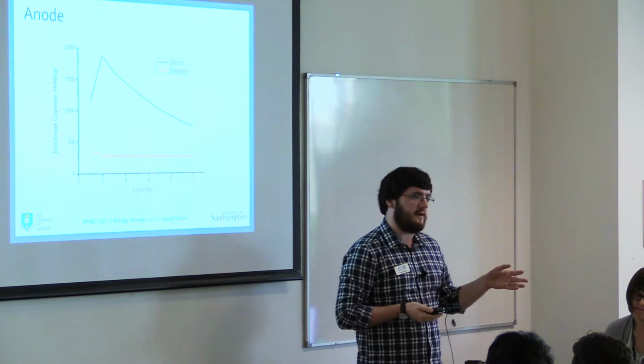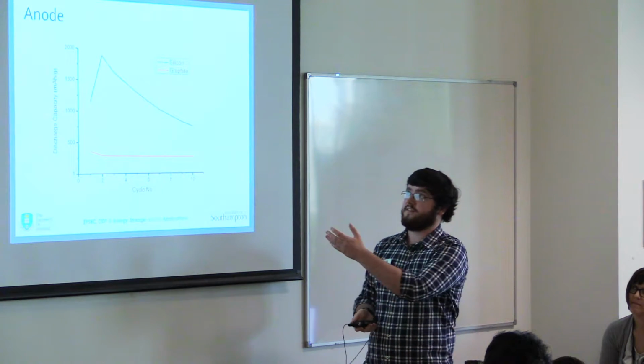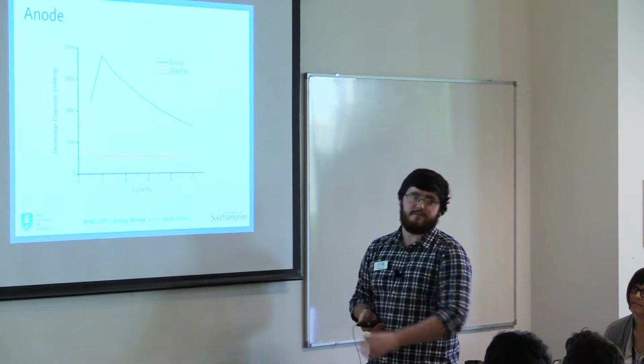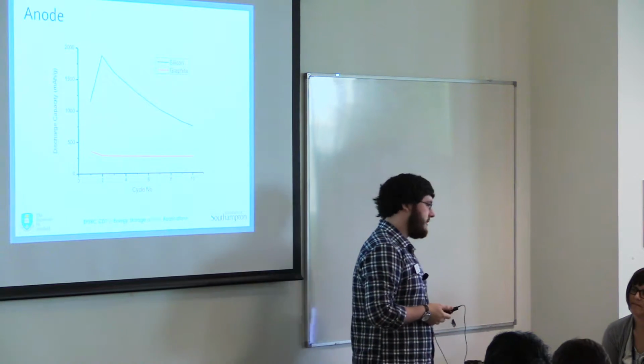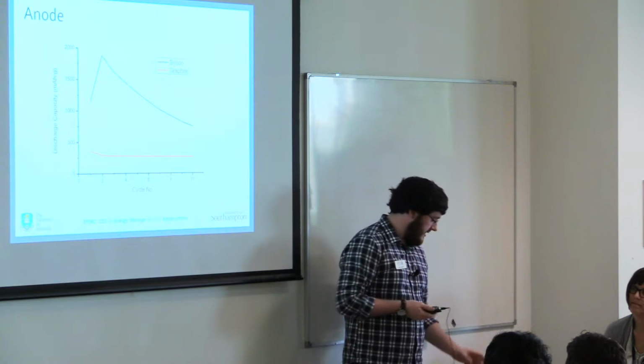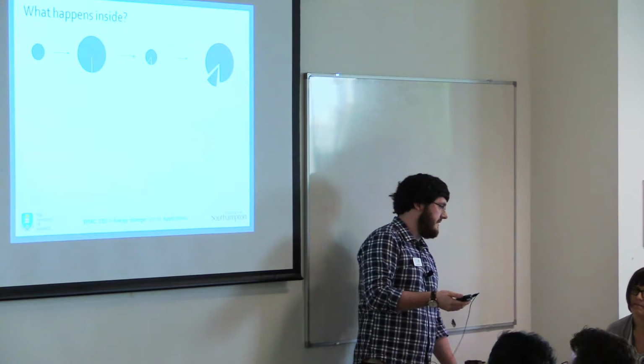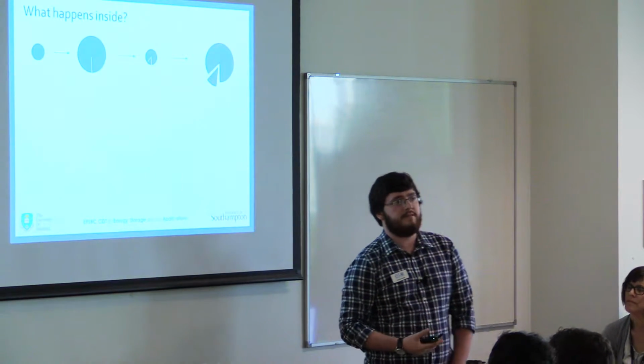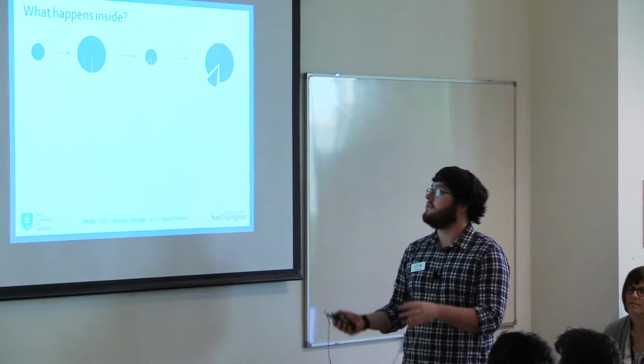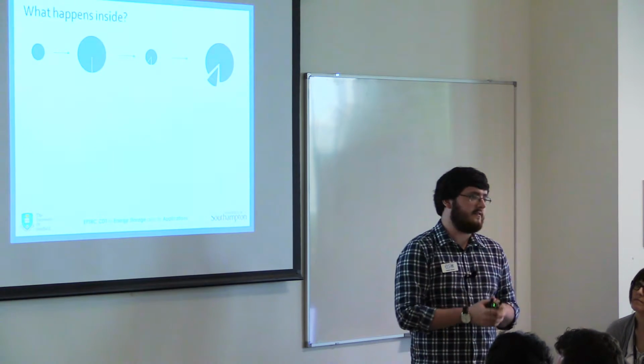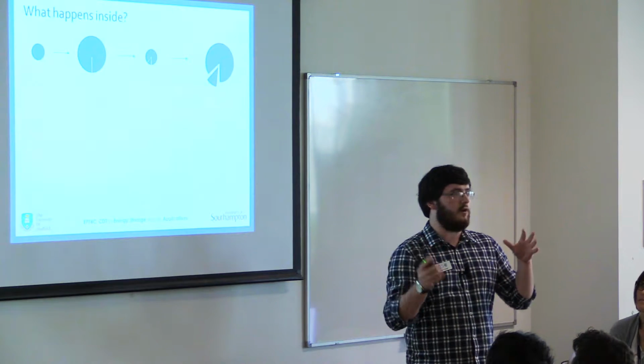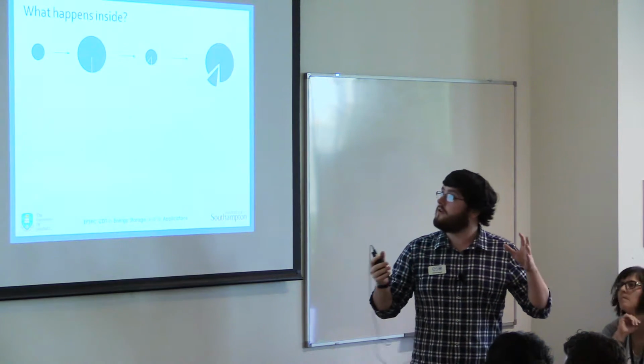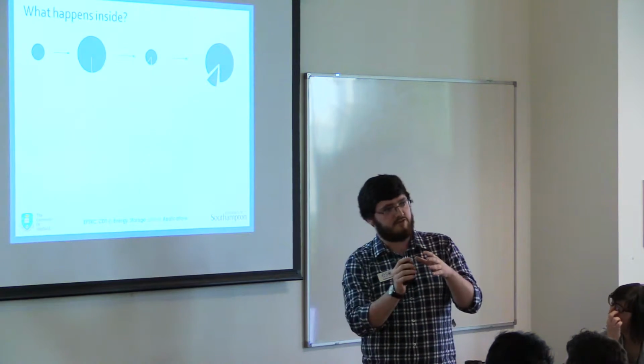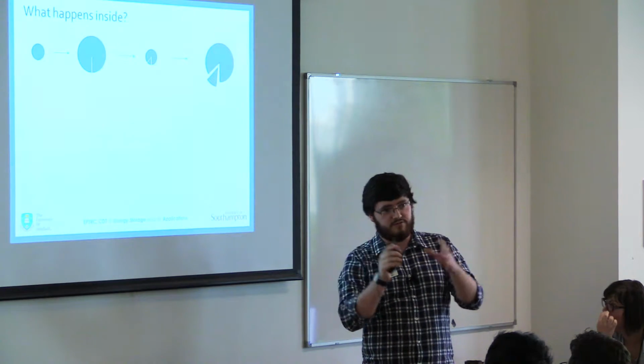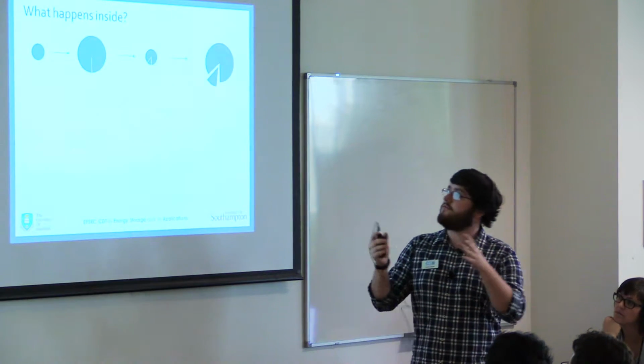I wish to increase the capacity of lithium-ion cells by using silicon anodes, but obviously we've got severe cyclability issues. So how do we go about this? First we have to understand what's going on inside the cell. When you're charging your cell, the lithium ions enter into the silicon structure. The silicon structure expands, increasing in volume by about 400%. You then discharge your cell, it contracts, charge it again, it expands, discharge it, it contracts. You do this over and over again.